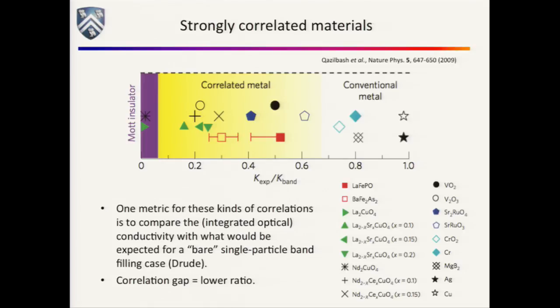So this ratio that he likes to talk about, this K, is some sort of integrated spectral weight of the Drude peak of the actual measured thing relative to what you'd expect from free electrons. And what you find is that in systems like silver and copper, this ratio K is basically 1. So it does make sense to think of these things, in this metric, as pretty uncorrelated. Vanadium dioxide in its metallic state is somewhere at around 0.5, and that correlates with the fact that it's a rather strange metal.